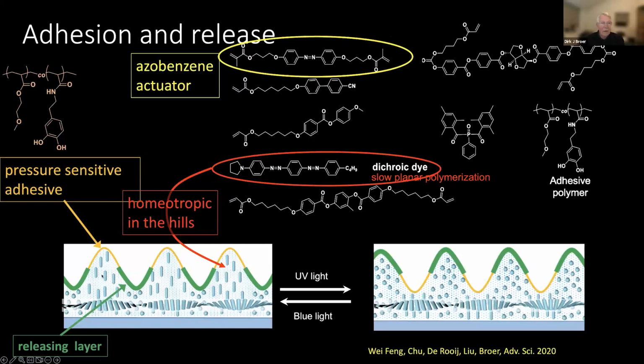So again, we create our system here with the corrugated structure, again having the azobenzene that we are using for the actuation, and we added also a dichroic dye, which is also an azo, for the controlled diffusion processes during the polymerization process.